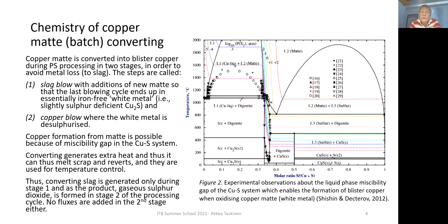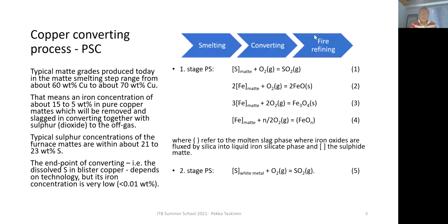So this is an enabling scientific background for why copper converting from molten copper matte is possible. And really it is done in two steps. First, slag blow, where we are oxidizing iron and forming slag. And then in the second step, we are oxidizing only sulfur and not actually generating slag, but only gaseous sulfur dioxide. So the reactions are here.